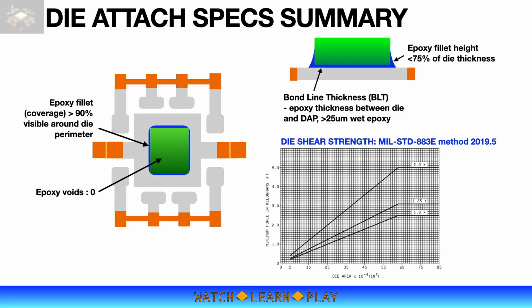Die shear strength is done after epoxy cure, which is a test of die adhesion to epoxy, and also the epoxy adhesion to lead frame or substrate. A good die shear result will have sheared die as break mode. You should refer to mil standard specs for minimum shear force requirement.